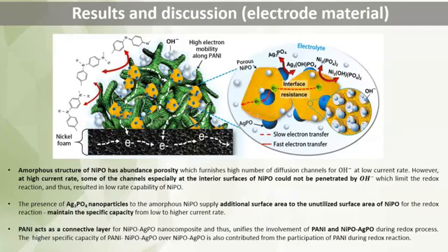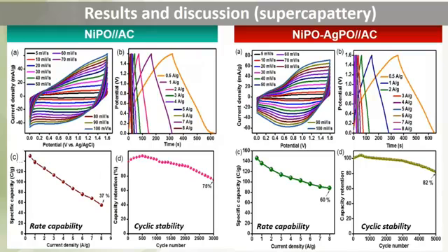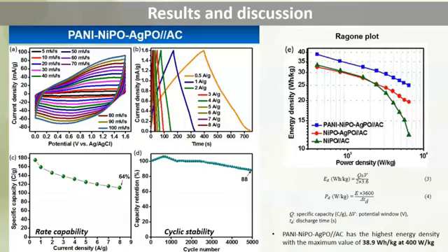supply additional surface area to the unutilized surface area of the nickel phosphate. Whereas the polyaniline will act as a connective layer which unifies the involvement of PANI and nickel phosphate, silver phosphate. And we can see some of the results of the supercapattery, where the rate capability and also the cyclic stability of the system with nickel phosphate and silver phosphate is improved. And the ternary nanocomposite shows the highest rate capability and cycle stability, where the highest energy density with the maximum value of 38.9 watt-hour per kilogram at 400 watt per kilogram is observed.